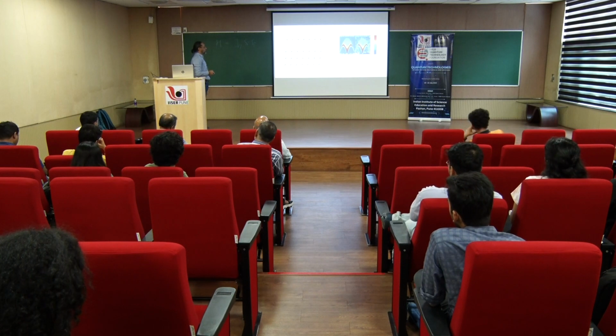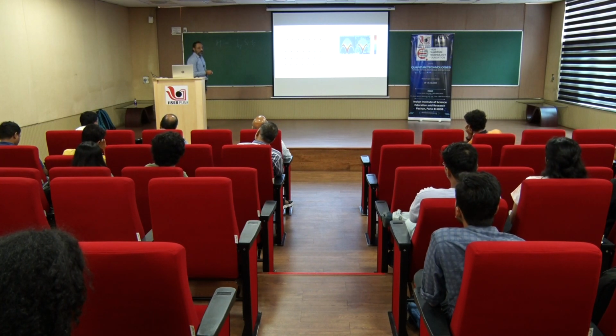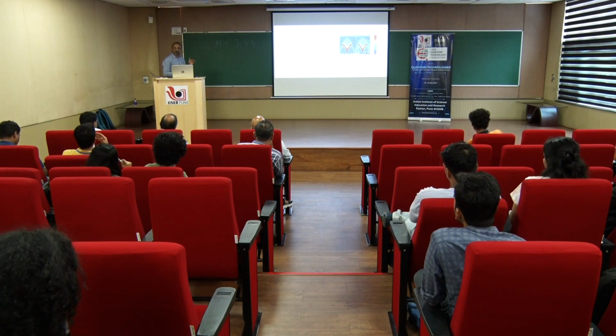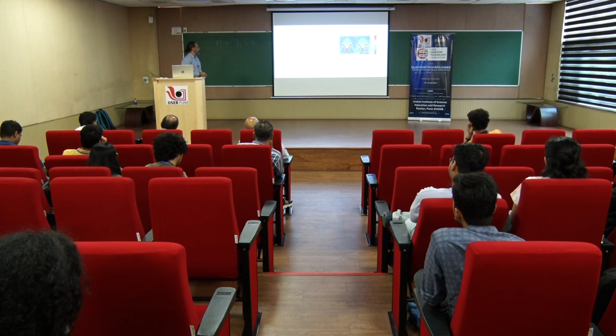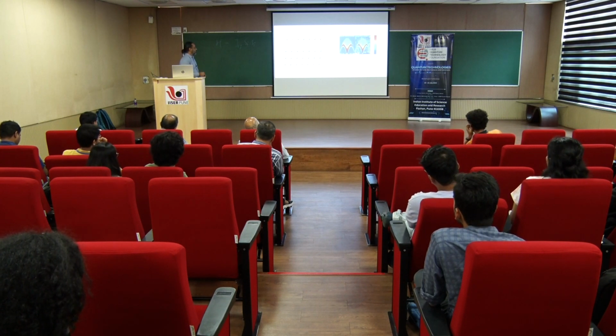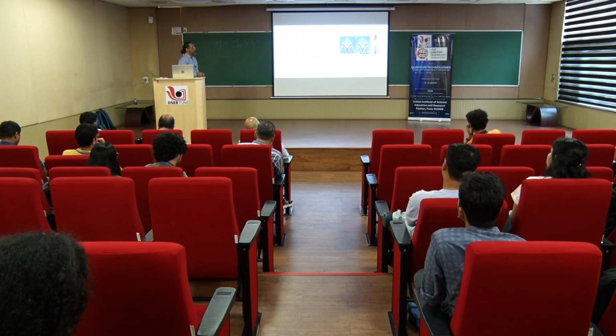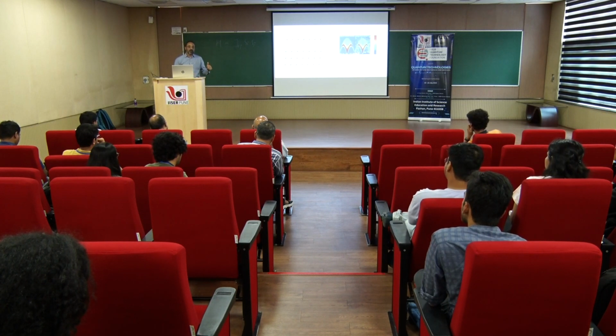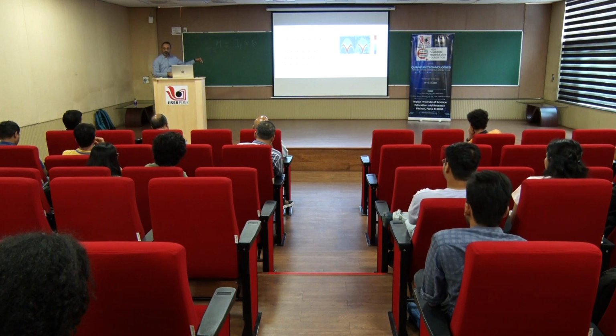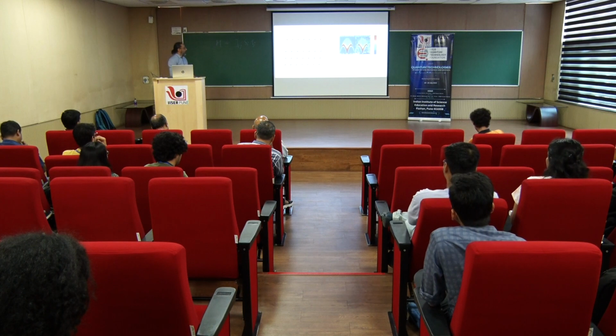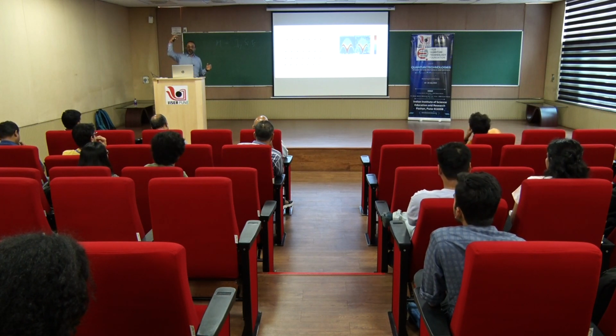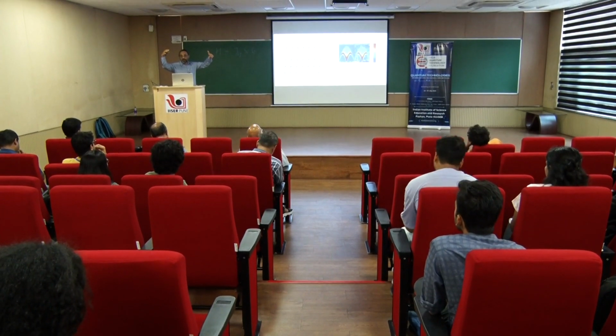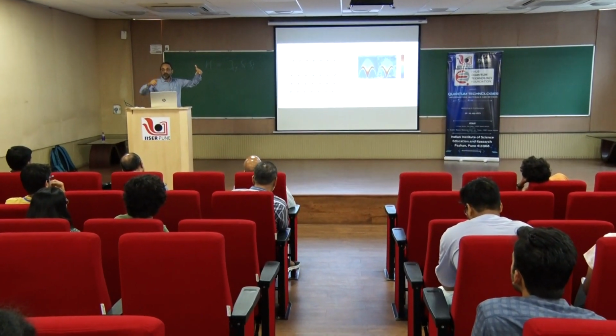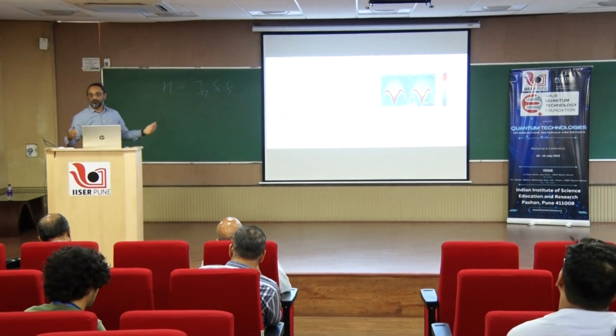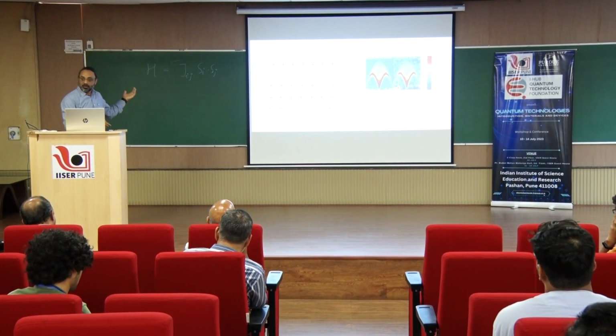A neutron comes in, interacts with the spins in the chain, and then goes out with less energy than it came in with. That is why it is known as inelastic neutron scattering, and the energy that it has lost to the system is actually the energy that the system has gained. So by calculating the energy difference between the incoming and outgoing neutron energy, you would know how much energy has been given to the system. That is the y-axis of your excitation spectrum. And by measuring the change in momentum, because you are sitting with a detector and you know where the source of neutrons is located, you know the k vector of the incoming neutron and the k prime of the outgoing neutron, and the difference of these two would give you the momentum lost to the system.